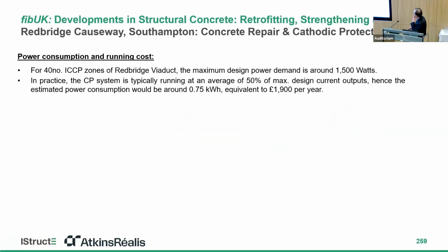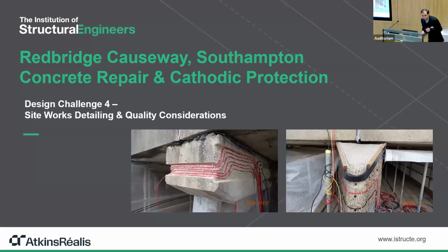Just to touch base on the power consumption, we get this question quite a lot. The Redbridge Viaduct had 40 ICCP zones, and the current demand, or power demand, was about 1.5 kilowatts. In practice, we found that the system normally runs at about 50% of the capacity. The cost of that over 1 year would be about £1,900, which may sound a lot, but compared to the ongoing concrete repair works, it's basically insignificant.